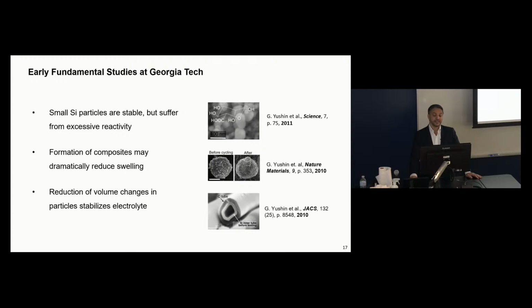Then we also realized that if you form composite materials, you can overcome volume changes at the composite particle level. And finally, we realized that if you have this core-shell morphology of the particles, when you have a shell and you have porosity within silicon that can accommodate this well, and the outer dimensions of the particles may not change, if you have constant outer dimensions of the particles, then in this case, the SEI, or this solid electrolyte interface, can be made very stable. And so with this in mind, we started the company.